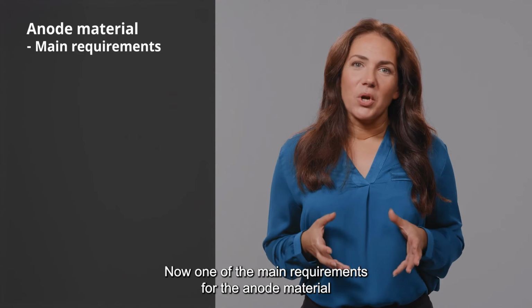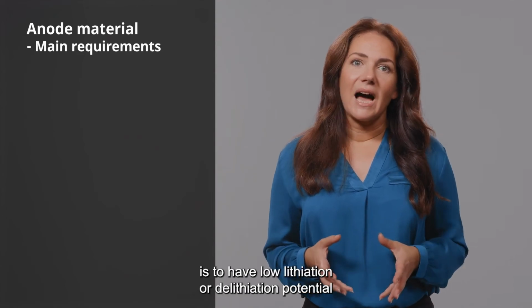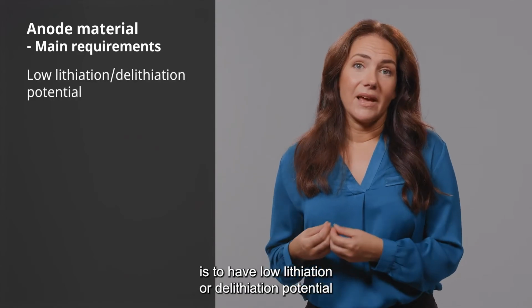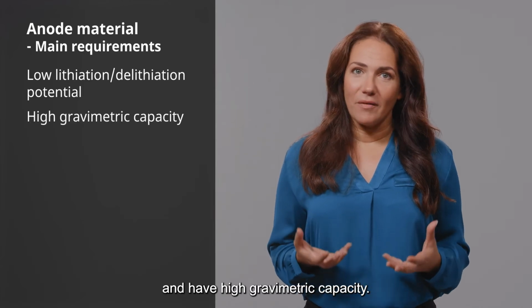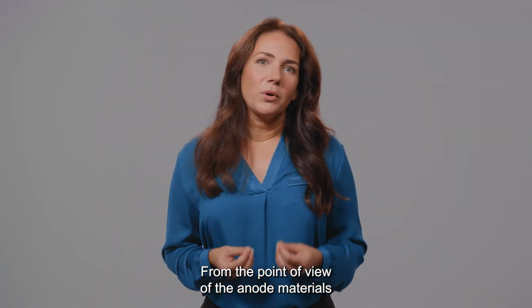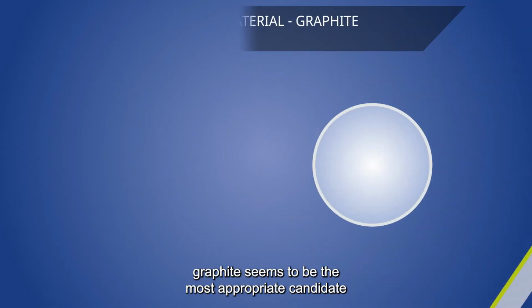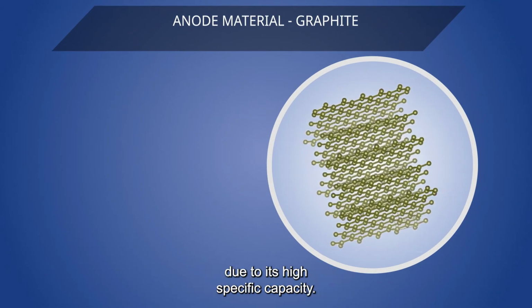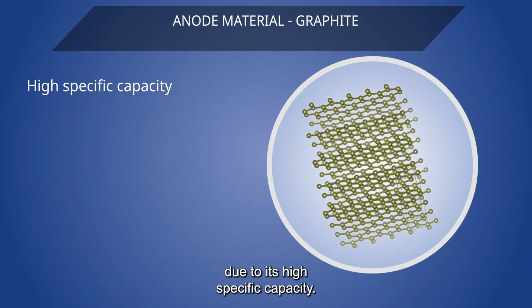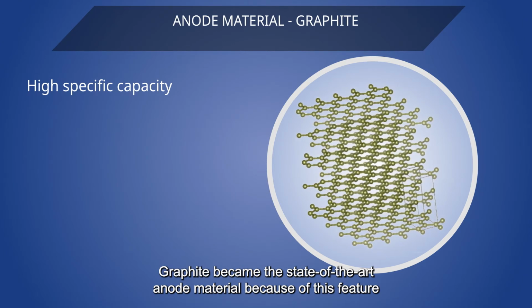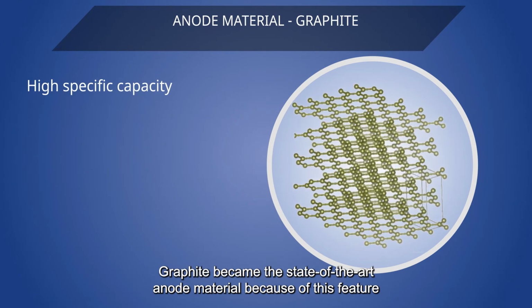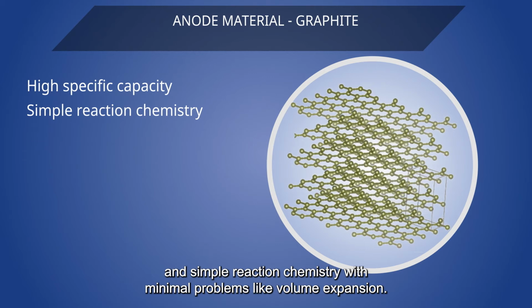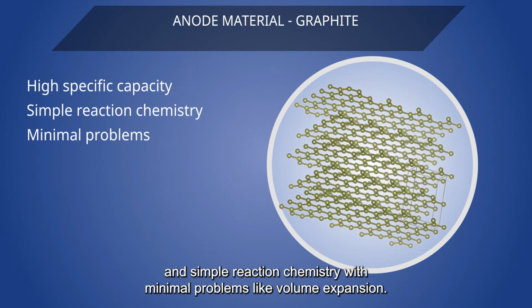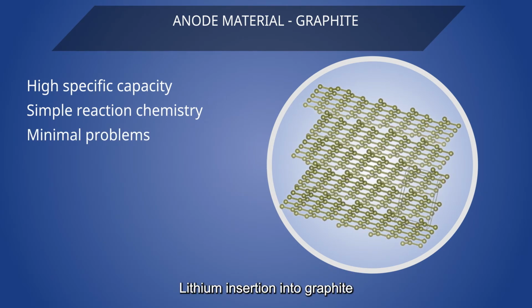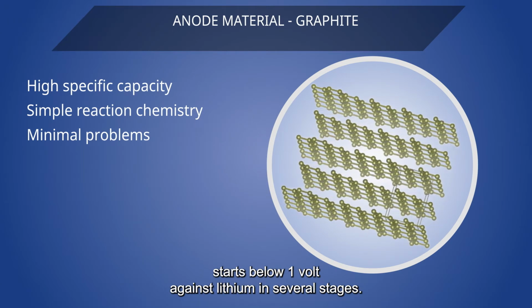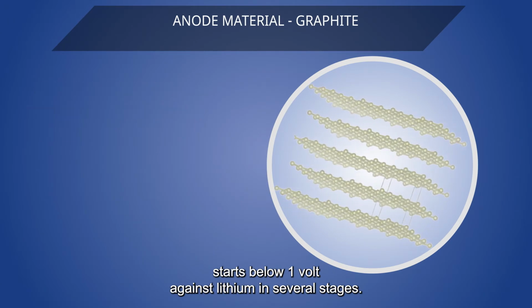Now, one of the main requirements for the anode material is to have low lithiation or delithiation potential and have high gravimetric capacity. From the point of view of the anode materials, graphite seems to be the most appropriate candidate due to its high specific capacity. Graphite became the state-of-the-art anode material because of this feature and simple reaction chemistry with minimal problems like volume expansion. Lithium insertion into graphite starts below 1 volt against lithium in several stages.